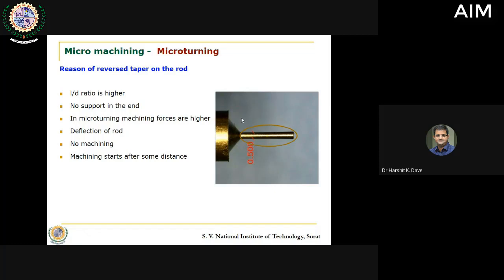One such case I want to specifically highlight. Here what happened was, at some position we could measure the diameter of exactly 0.5 mm as per our requirement. 500 microns was possible. However, what we found is, here there is a taper. Okay, so here the dimension increases. It is something like this.